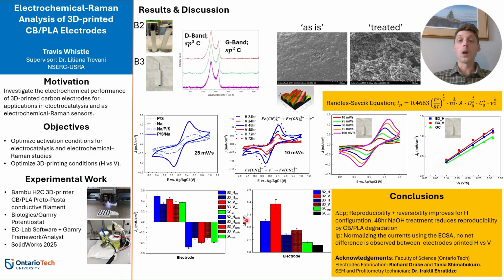The bar plots on the bottom correspond to the current density and delta E plots respectively. Sample size for B2 is 10, that for B3 is 5. The results show an improvement in reversibility for the B3 design with the brass wire, an expected result due to lower electrode resistance. The B2 designs show very high current densities, likely indicative of increased CB surface area after sodium hydroxide treatment, but more studies are required to gain more clarity on this conclusion.